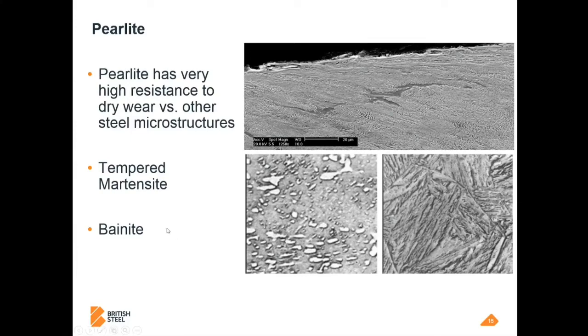There are some bainitic steels under development, but they've been under development for 30 years and they really haven't got much traction. And the wear performance is poor but tolerable. So for a 320 minimum Brinell bainitic steel, it actually wears faster than a 260 minimum Brinell perlitic steel, but only just. But they come with additional problems. While they're excellent at resisting rolling contact fatigue cracking, they're very susceptible to stress corrosion cracking and also self-propagating cracks with no fatigue cycle. Just the sort of things you don't want in a railway. They make it incredibly risky and they just haven't got any traction. So perlite will continue to remain the dominant microstructure, I believe, in this industry for the next, certainly my career.